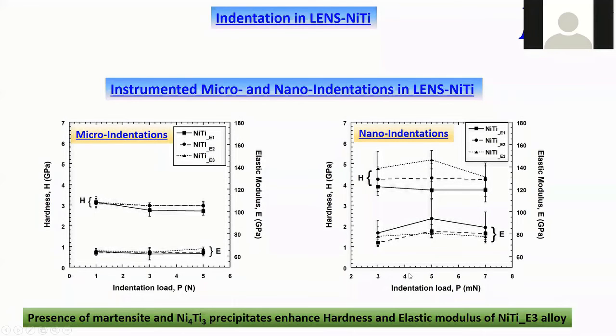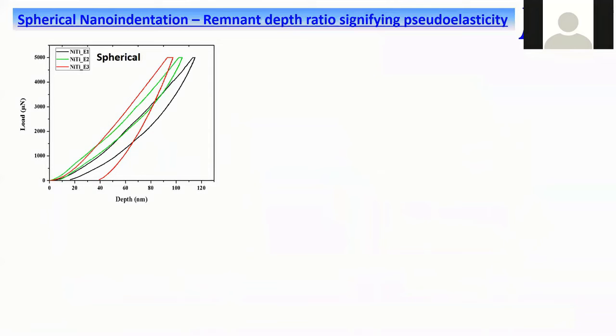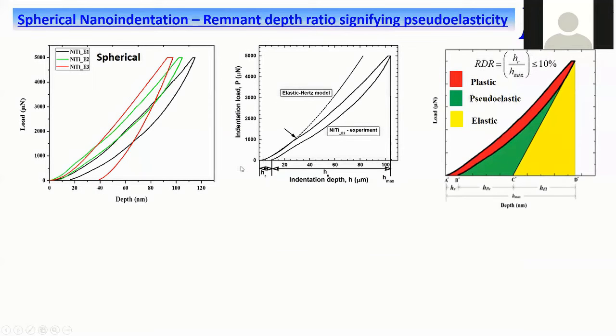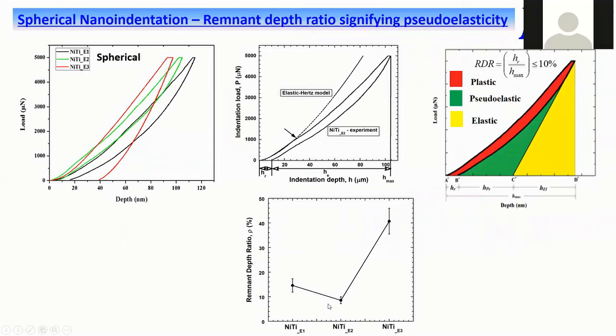From the mechanical property analysis at local scale, we predicted that something is going on with the one prepared with the energy density of around 50 joule per millimeter cube. We found out the recoverable deformation, how much deformation can be recovered. This is basically showing the opposite of that, the remnant depth. This red here signifies the remnant depth, the plastic deformation, and we have seen that this plastic deformation is least for the E2 alloy prepared with around the middle of the energy term, around 52.